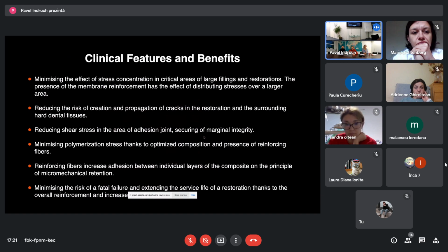Before I let my colleague Dr. Slavicek speak, I will try to summarize the clinical benefits of using fiberfill products. In brief, this includes minimizing the effect of stress concentration in critical areas of large fillings and restorations, reducing the risk of creation and propagation of cracks in the restoration and the surrounding hardened tissues, reducing shear stress in the area of the adhesive joint, securing marginal integrity, minimizing polymerization stress and polymerization shrinkage thanks to the optimized composition of the materials and presence of reinforcing fibers, which can dislocate the stress from polymerization shrinkage.